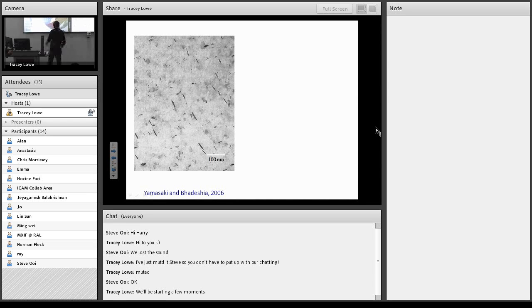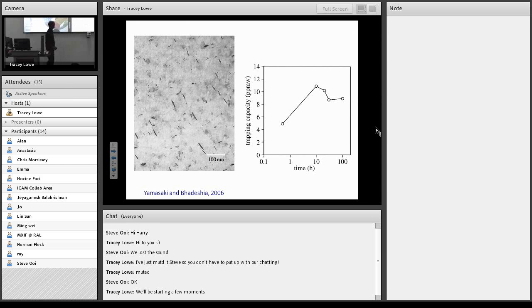Introducing these particles gives you a large trapping capacity. So this is a large trapping capacity where you're talking about, say, 8 parts per million by weight of hydrogen that can be absorbed at those carbides. And it more or less removes the static fracture problem from these bolting steels. So this has actually, for many, many years, been a commercially available product. And we want to do something like this for some of the work that we're doing in this BP-ICAM project.